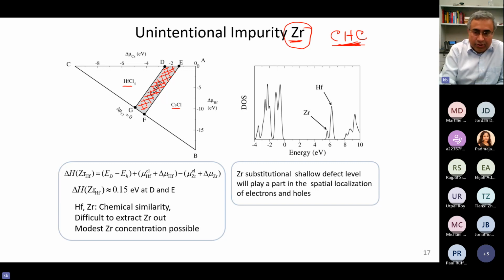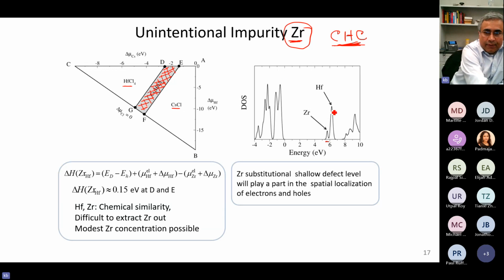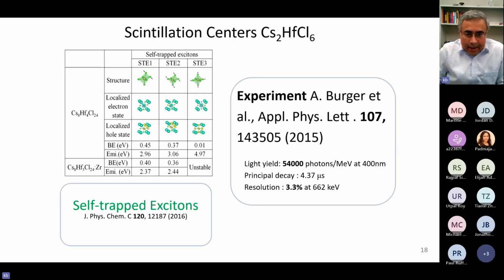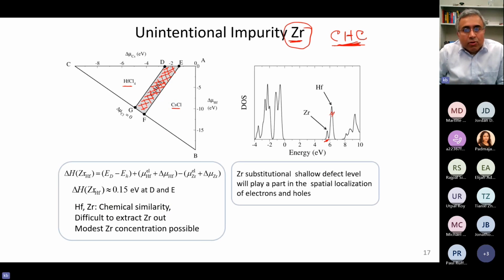And then on the electronic side, we indeed saw that when we add a little bit of zirconium to the crystal, it shows up as zirconium D states near the bottom of the conduction band, right there. We have hafnium normally at the bottom of the conduction band, and zirconium also appears along with the hafnium D states at a very similar energy. So it behaves almost as hafnium. That's what we found. That means zirconium will be mixed up with hafnium states like we see here, and therefore there could be some zirconium related emission as well.